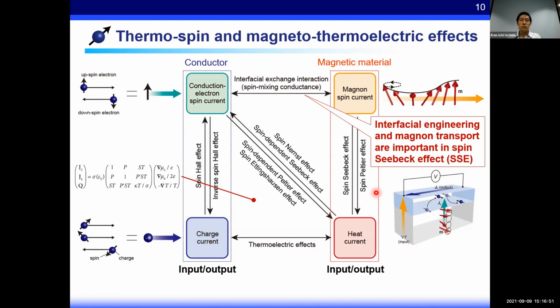The generated magnon spin current is then converted into a conduction electron spin current through the spin mixing conductance at the junction interface. The conduction spin current is subsequently converted into a charge current due to the spin orbit interaction or the spin Hall effect. Therefore, the spin Seebeck effect and the spin Peltier effect are essentially energy transport via the interfaces, and in fact, the improvement of thermospin conversion properties by interfacial engineering has been reported.